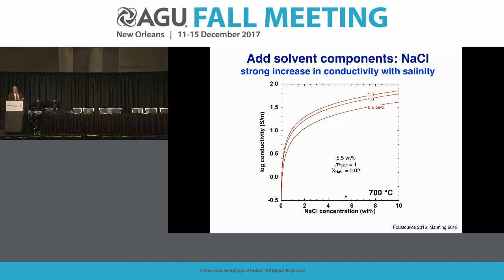Well, in terms of conductivity, this is, of course, obviously going to be important. And you can see that as we increase the concentration of NaCl at 700 degrees C, and we just pick a pressure, whether it's 5 kilobars or 15 kilobars, the conductivity will increase dramatically, even at very low concentrations of NaCl, but continue to do so as we get to very high concentrations of NaCl, as one might expect. These are all calculations that were made possible by a recent excellent paper by Foustoukos in 2016.